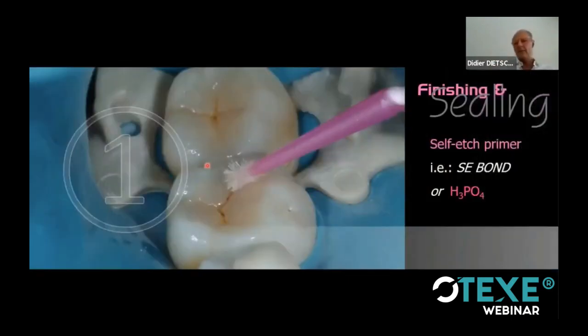The technique is very simple. You have two options. Either you use phosphoric acid, your normal enamel etchant, or what I found also more now around 15 years ago, that it works very well with a two-step self-etch adhesive like the Clearfil SE Bond. So I use a self-etch primer as a cleansing agent to clean the smear and everything that might prevent the hydrophobic bonding or the hydrophobic sealer to penetrate the defects.